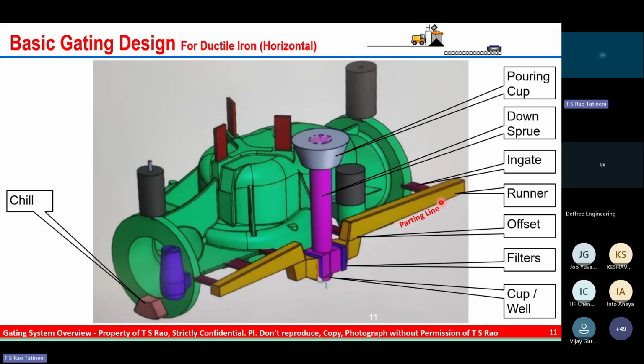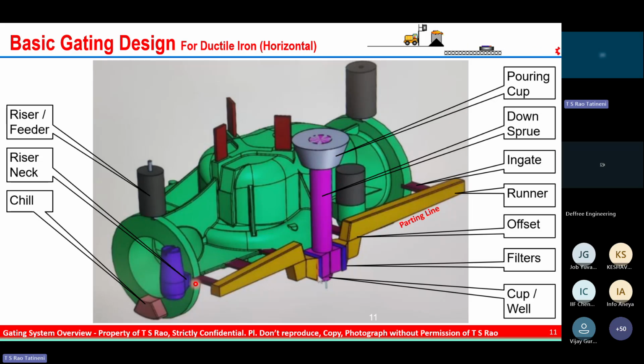Here on the other side, you can see the chill. The chill pushes towards the riser where the riser gets fed. Here in this case, it is a sand riser. And this riser neck is connected to the casting flange. These are the exothermic sleeves. You can see the sleeves are connected with a pipe. It gets open through the roof. And we have flow offs.